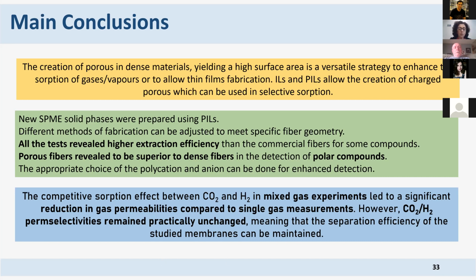On the other hand, when we try to separate CO2 from H2 and CO2 from N2, as I showed in the last slide, I show you that we can also greatly increase the permeance of the gases in these membranes. And it's really a matter of being patient and trying to refine the conditions of the membrane casting and of the pore forming. I'm sure that we will be able to come up with asymmetric membranes, or who knows, porous membranes where we can have an increased selectivity.